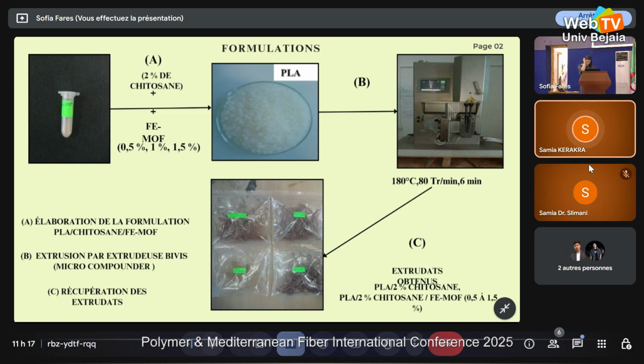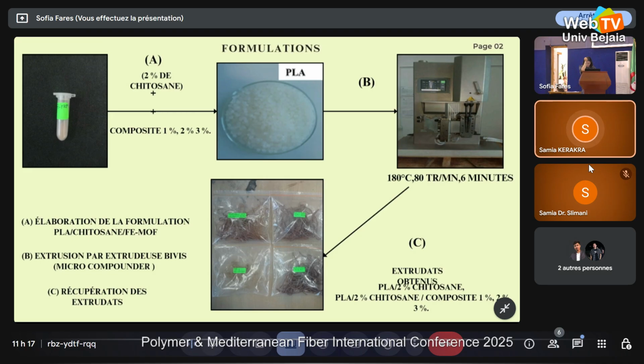It's worth noting that the Chitosan used in this study, prior to use, was washed with distilled water, dried at 55 degrees Celsius for 24 hours, and subsequently ground and sieved through a 200 micrometer mesh to obtain uniform particle size suitable for composite preparation.